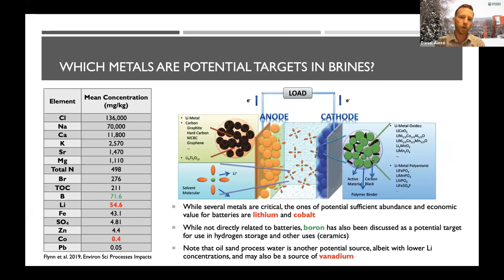So here we're looking at a brine with a salinity on the order of 5 to 10 times that of seawater. And the thing we're shooting for is lithium in this case. Lithium in this particular brine is at about 55 parts per million. So this really is a traditional needle-in-the-haystack problem, where if we're going to make an industry out of this, we have to have a highly selective technology which strips out the lithium while leaving all this other stuff that we don't want behind.